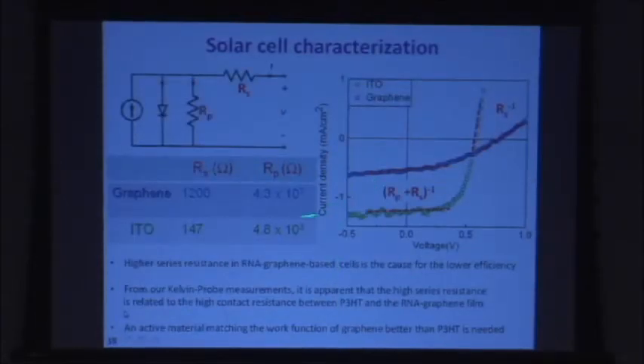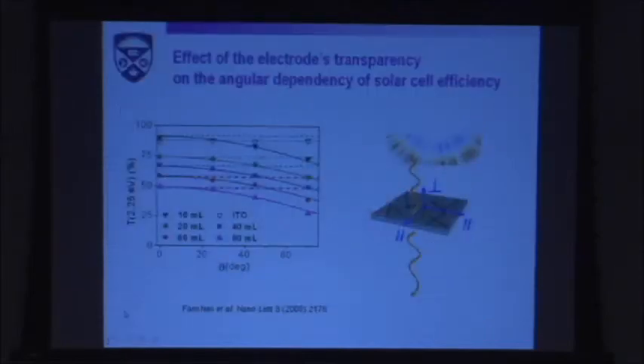And you can see also that this is reflected by this mismatch in work function, by a higher contact resistance between the active material and the electrode. That means a higher series resistance if I make a diagram of my solar cell.